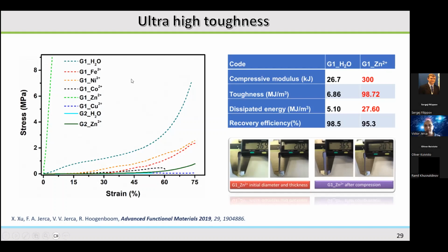we expected this to happen for iron, but actually zinc has the advantage that it forms thermodynamically stable complexes with the terpyridine. However, they are kinetically labile, and this allows the dissociation and reformation of the complexes throughout, and the formation of a more efficient network compared to when using iron.